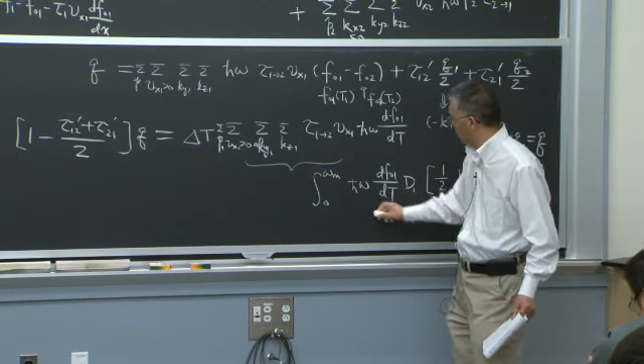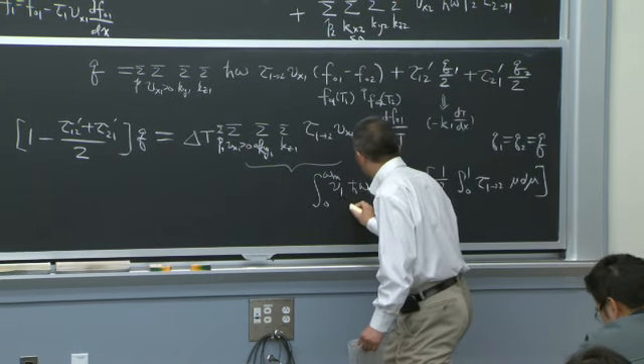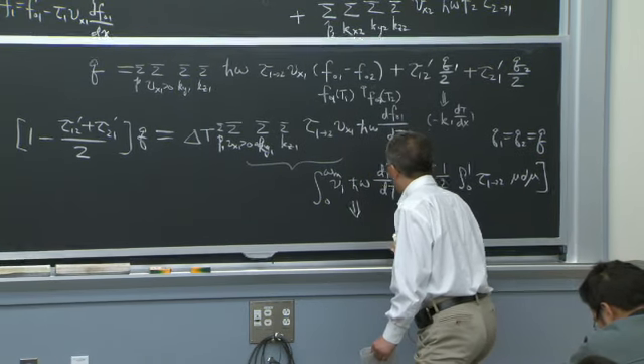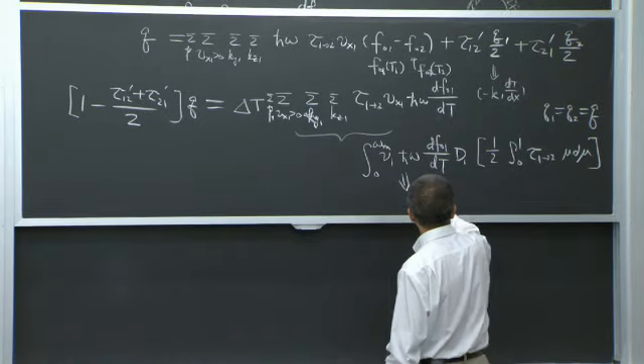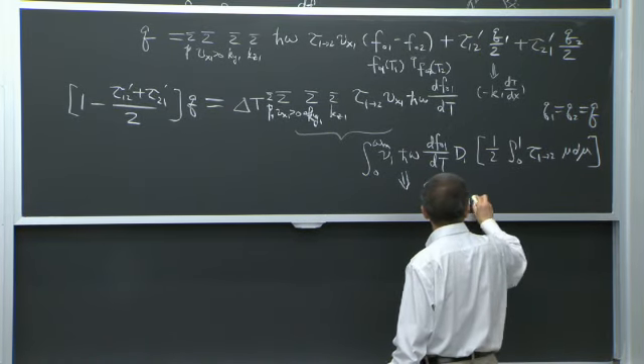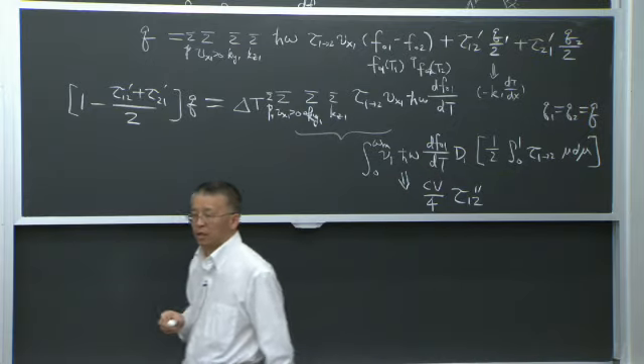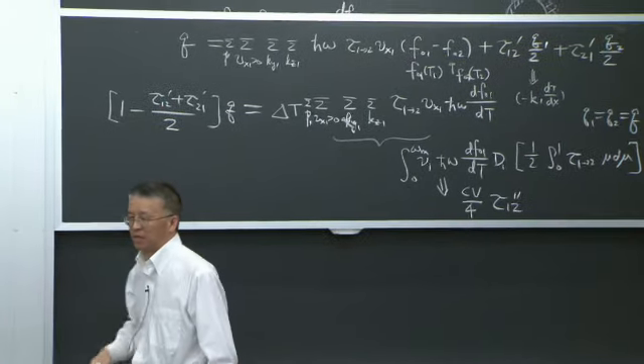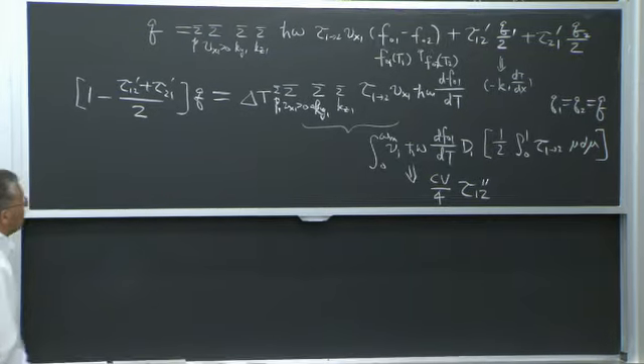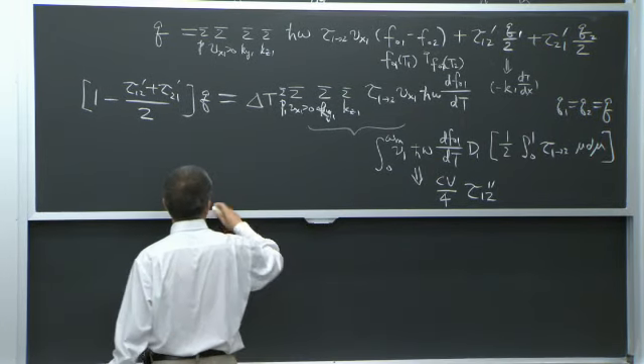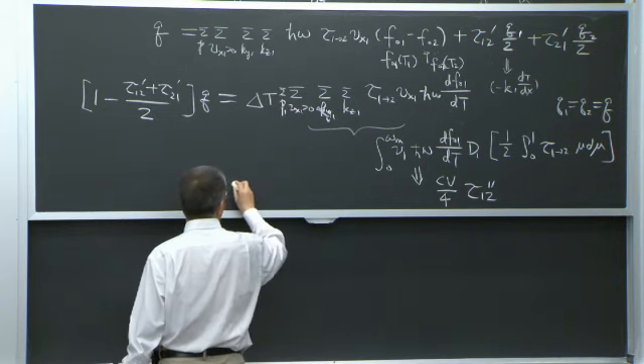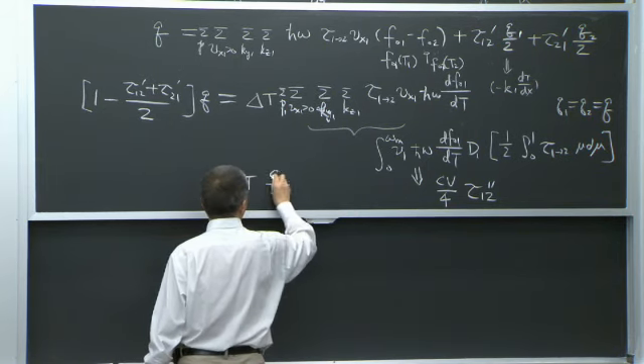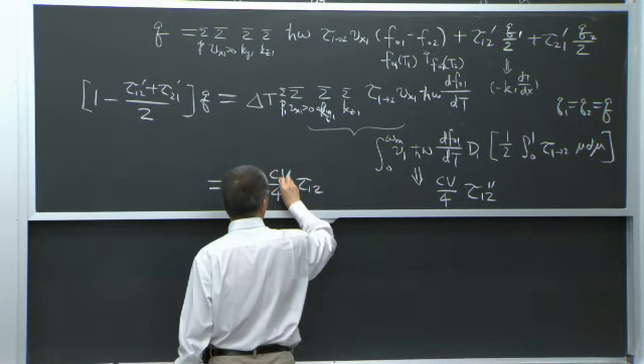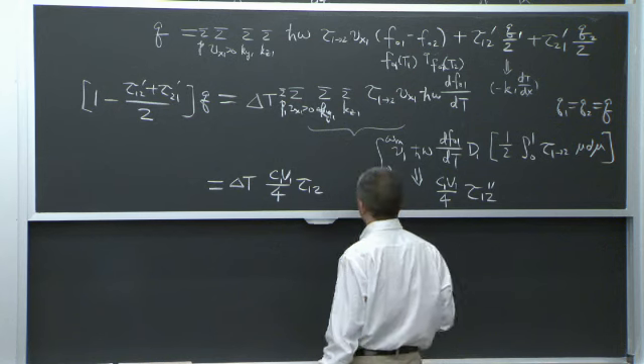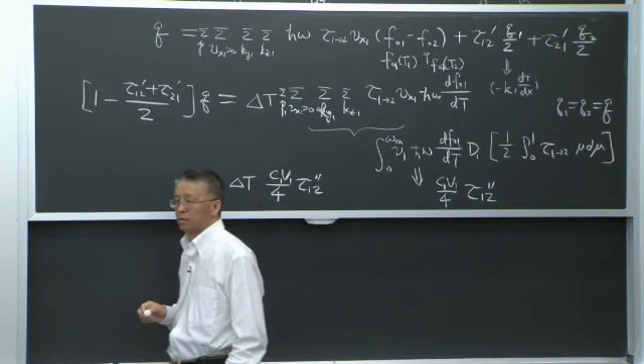This gives me the specific heat. Oh, I forgot here is V1. So altogether, I can write this as 1/4 C times V, and times tau 1 to 2, a different weighted average in terms of angle. Here I use a prime, and there I use a double prime. So if I write it together, it is delta T, 1/4 C1 V1 and tau 1 to 2 on the first side, and tau one two double prime, right?